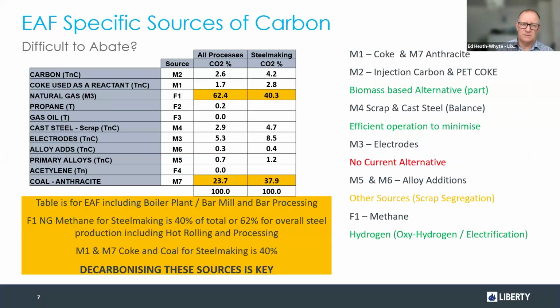So this is where CO2 comes from, or was emitted from, in the process. So we have different sources of carbon, and these are all from our UKCCS registry. So we calculate every year our tons of CO2, and those are verified, and we report those through the emissions trading scheme. So we've got carbon additions, coke and coal, so M1 and M7, natural gas, propane, gas oil, electrodes, alloy additions, primary alloys, and a small amount of acetylene. And you can see from all processes there that natural gas is the biggest, and coal is probably the second largest, and then for steel making similarly.